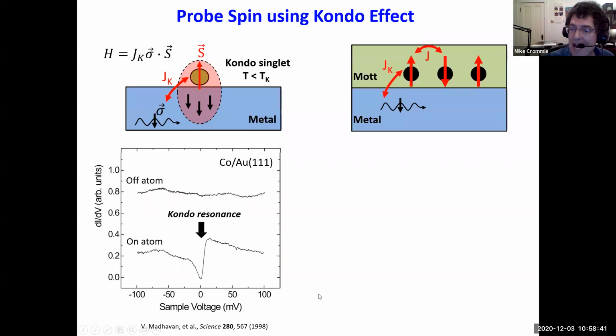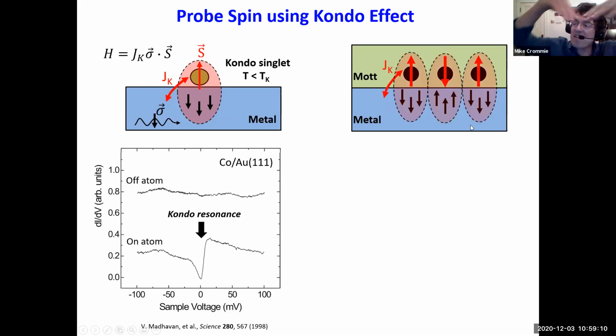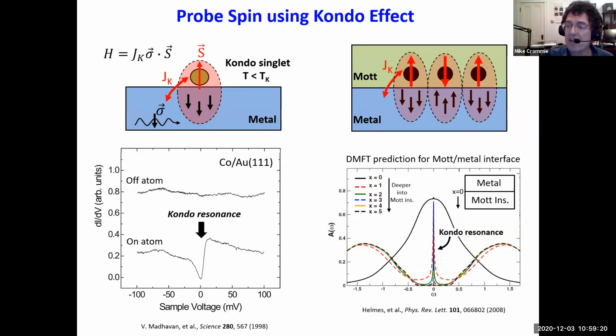But now let's consider what happens if I put a Mott insulator on a metal. So now you still might expect the local spins of the Mott insulator to interact with the itinerant spins of the metal, but you also have the interaction between the spins in the Mott insulator. So if the Kondo interaction overwhelms the interspin interaction of the Mott insulator, then you might expect that the Kondo effect will win, and then each of these spins will be screened by the metal. That's a very intuitive picture. And if you do a more sophisticated, detailed calculation using dynamical mean field theory, it's been predicted that this is precisely what should happen.